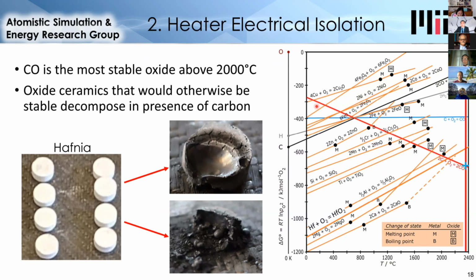The way you can think about this is the stability of hafnia versus carbon monoxide, which are the two oxides that are competing here. This plot on the right is called an Ellingham diagram and compares the stability of different oxide materials. And so the lower a material is on the vertical axis, the more stable. This means it has a larger negative Gibbs free energy. And so carbon monoxide is this downward sloping red curve, and you see that as temperature increases, it becomes more and more stable, unlike all the other materials which become less stable. And because of this, around 2,000 degrees Celsius, even the most stable oxide, which would be hafnia or magnesia, become unstable in the presence of carbon monoxide, and that's what we observed in this experiment.